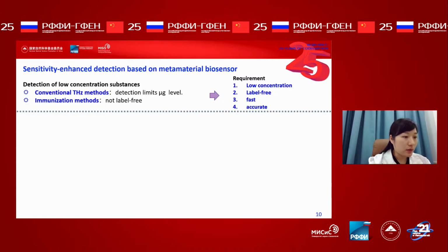During this process, we found that the concentration of biomarkers is usually very low. The conventional terahertz method can only reach detection limits at the microgram level. The immune method is labeled, which is not conducive to the second measurement. Therefore, we need a new solution which not only achieves low concentration, label-free detection, but is also fast and accurate.